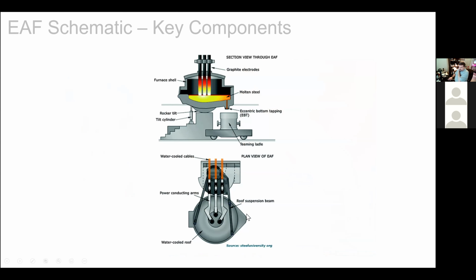And we have these arms, and we have a system using hydraulics to adjust the position of the arms in order to maintain a current set point within the furnace. And as I said, the power is supplied from a transformer, which is contained in the vault. That transformer will typically have several different voltage taps, because at different stages of the melting, you might want to use more or less voltage. Voltage is essentially equivalent to the length of the arc that you see in the furnace. And the whole concept behind this kind of melting is joule heating.